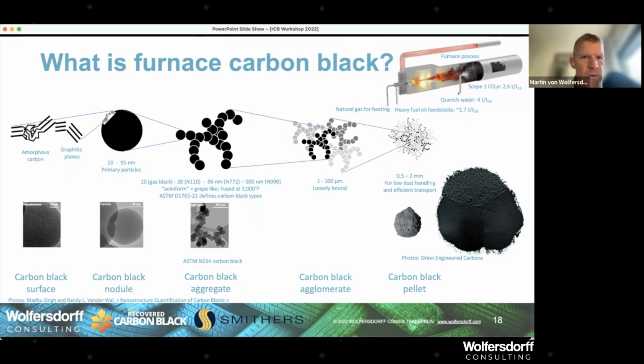And in order to manage the right particle size for the particular carbon black that we are manufacturing, we need to stop the reaction. And the reaction is stopped with a water quench, which is a very sudden cool down by evaporation of that water. This process, the furnace process, runs very hot at about 1,800 degrees. In order to increase the efficiency and the yield, the industry is now going as high as 2,000 degrees.